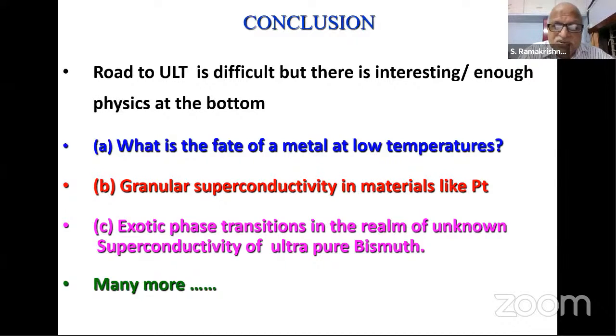Gold, there is a chance because the electron-phonon coupling constant is a little larger from the theoretical side, and it is predicted to be a superconductor at 50 microkelvin. We have tried to see that, but it didn't show superconductivity, and we know the reason for it because it has 0.5 ppm of manganese. These magnetic elements are really bad for such superconductors. So 0.5 parts per million of manganese in the so-called pure gold kills its superconductivity. All these noble metals have very weak electron-phonon coupling, which is why they have very high conductivity. So they will never become superconductors at low temperatures.